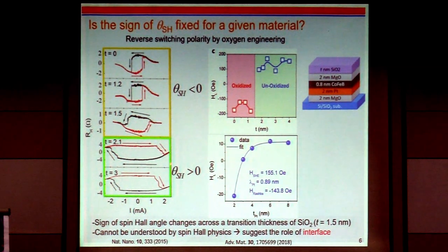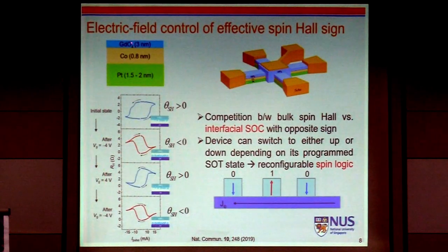Above 1.5, we see a typical positive spin Hall angle in terms of the anomalous switching signature. But below 1.5, we see a negative spin Hall angle. Once we extract the magnitude, we found it's pretty much the same. Looking at the longitudinal effective field, below 1.5 it is about negative 150, and above 1.5 it is about positive 150 Oersted. So it shows that once we do some kind of oxygen interfacial doping, we can change its effective sign with similar magnitude.